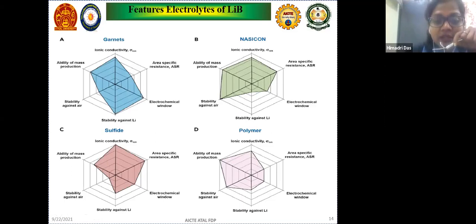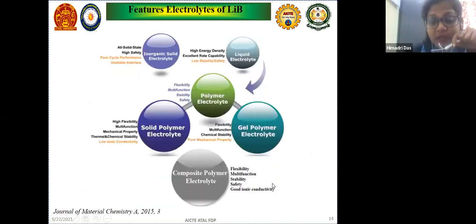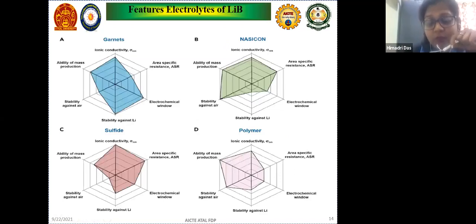So this also has to be developed, like adding other electrolytes. As well as when we go for NASICON electrolytes, as garnets are lithium based electrolytes, NASICON is a sodium based solid electrolyte. So that also faces a lot of stability issues, and its potential window is less than the garnets. So people are developing NASICON towards improving the potential window and all. Similarly, when you focus on polymer electrolyte, as I mentioned in the previous slide, polymer electrolyte is very nice, but it also has a low potential window, because the polymer gets degraded, and stability against lithium has to be focused on for polymer electrolyte.